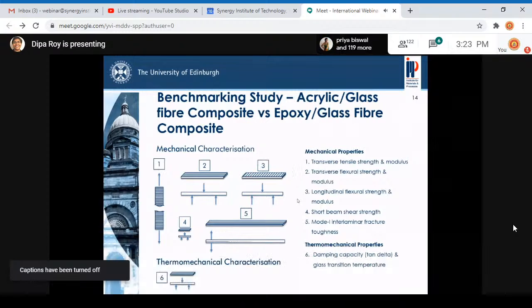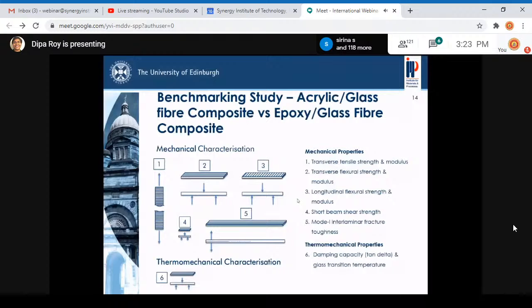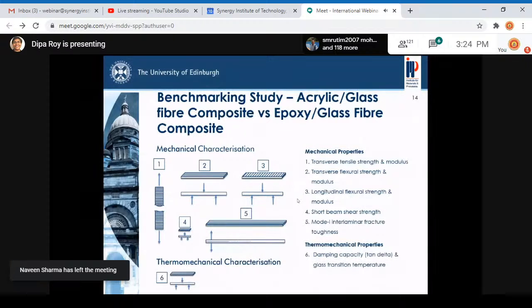So the interface has to be strong so that we can have effective stress transfer at the interface of the fiber and the matrix. When we select the reinforcement fiber, here glass fiber, it is important that it has the right sizing agent which can actually interact with the matrix. So we selected a glass fiber reinforcement fabric which is multi-compatible, meaning it is compatible with epoxy resin as well as acrylic resin.